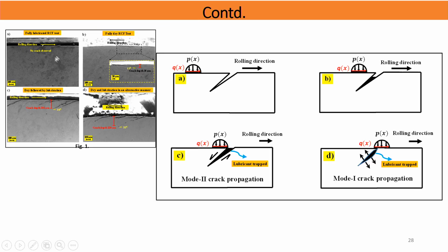Now what we understand is that as this contact moves forward, you start pressing this crack, if a small crack has been formed. As you reach the edge of it, you create a kind of mode 2, because this side will be pressed down and this side pressed up, so at this tip the crack will be almost mode 2. Now this is something which many of us can pick up and do more work on. A lot of it has already been done also, but we can use it in our models.